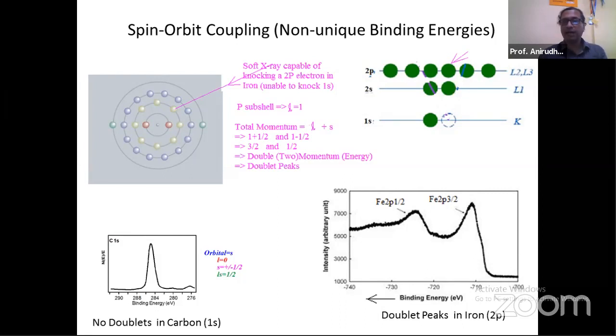If the binding energy values quoted in your database are referring to Fe 2p 3/2 values, then obviously you will have to look into the Fe 2p 3/2 binding energy shift and their values. Whereas if the database that you are referring to refers to Fe 2p 1/2 values, then obviously you should be looking into the other peak, which is related to the Fe 2p 1/2 value. So the choice is yours, but it is dictated by those considerations.